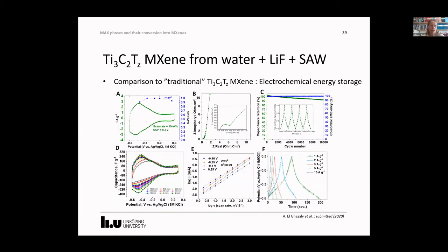To demonstrate that this technique provides a material similar to what has been synthesized before, we produced an electrode for initial analysis with respect to electrochemical energy storage. I will not go into detail, but charging mechanism, measured volumetric capacitance, and also conductivity fall within the range reported previously for this material.